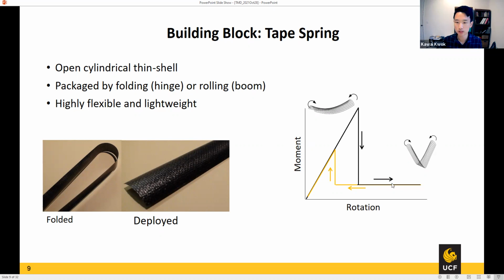And so this is a very nice behavior to exploit, because you really want to look at that regime where you have an increase in rotation. That means a large shape change, but what you need to provide is a very, very small moment. So this is a great way to make a deployable structure, because the loading applied is not proportional to the deformation or shape change you get, right? The loading is always low. So the snapping instability is really the thing behind all this work.